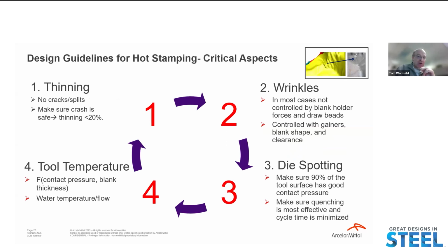Thinning values, whether measured or predicted through the simulation, are a strong guide for developing successful stampings. In addition to the FLD, a maximum thinning guideline of 20% is often applied to ensure successful stampings and avoid issues in performance. Controlling wrinkling in the hot forming process is one of the key challenges. As blank holder force control and draw beads are avoided, wrinkling is controlled with die geometry, and therefore strong communication between the part designer and manufacturing is strongly recommended.